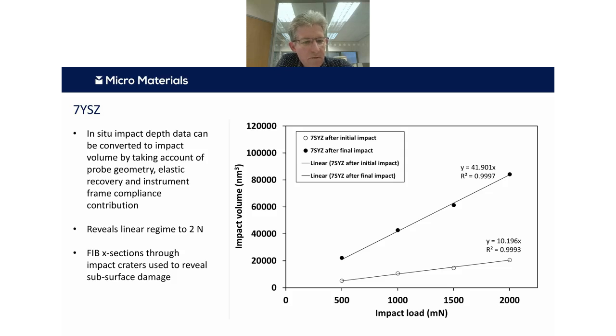We normally do report impact depth data, but one of the things we thought might be interesting is whether we could directly convert this to impact volume. Provided we take account of the sphericonical probe geometry, and correct our depth data for elastic recovery and the instrument frame compliance contribution, we essentially get an impact volume for each of these depth measurements. When we do that on the 7YSZ, we see very linear traces of volume versus load, which go through 0, 0 very accurately, with R squared in excess of 0.999.